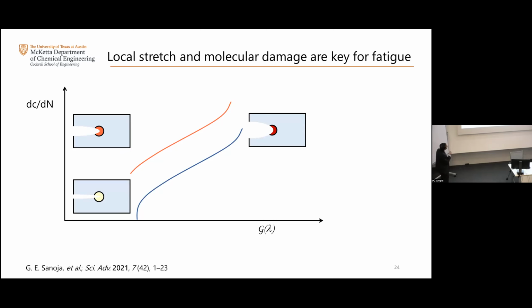So now if you compare two systems at the same G, because this system is actually tougher, effectively your crack tip opening displacement, or the local stretch ahead of that crack tip, is going to be larger on each cycle that you apply. So what that means is that because you have a larger stretch ahead of the crack tip, the probability of breaking a polymer chain ahead of the crack tip on each cycle increases, giving you more damage and lower fatigue resistance. So again, I hope that this scheme summarizes the big picture of what's going on. At low stretches, if you have a strain hardening system, effectively you have low damage. As you increase the stretch, the damage increases. And if you make the system have a lower strain hardening or be more stretchable, then you actually have more damage and lower fatigue resistance.